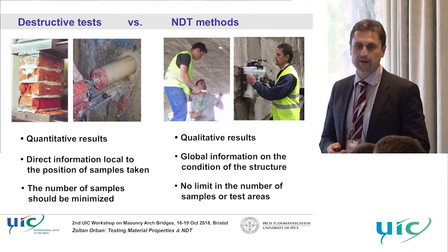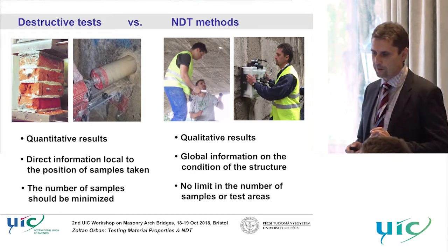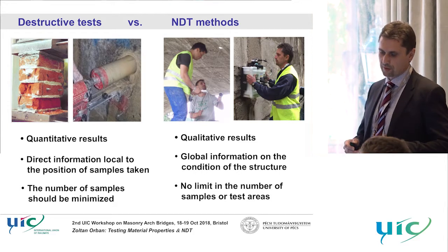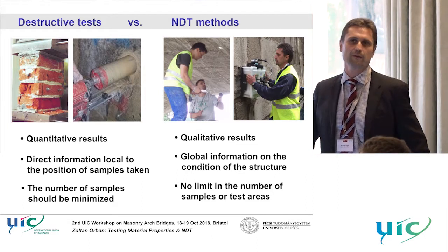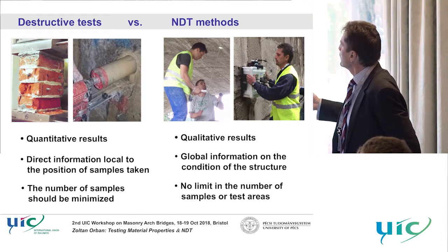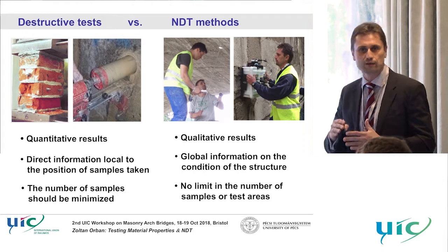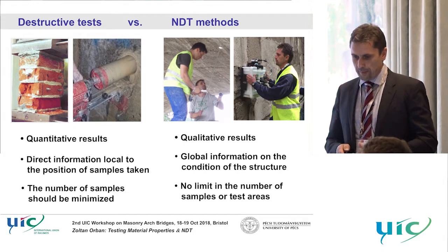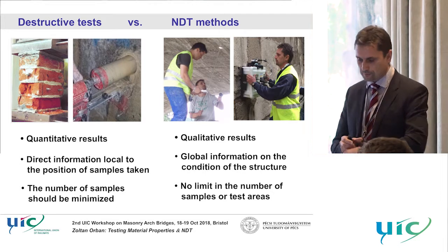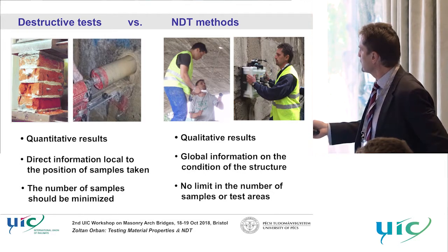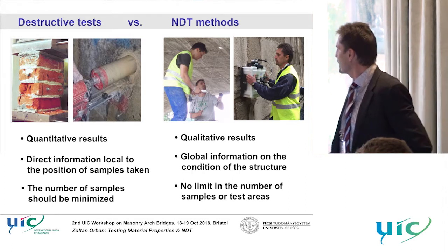Destructive tests give direct but very localized information at the position of the samples taken, while NDT methods are expected to give information on the condition of the whole structure — global information. Endoscopy, for example, can give information on the condition of the whole arch and what is behind it. In destructive tests the number of samples should be minimized, whereas in NDT there is no limit in the number of test areas.